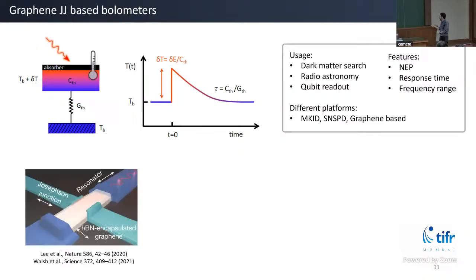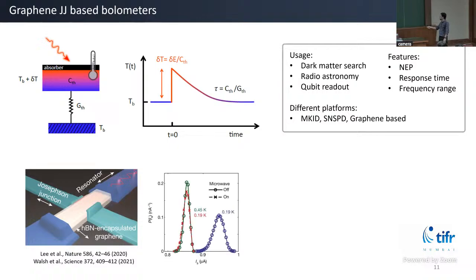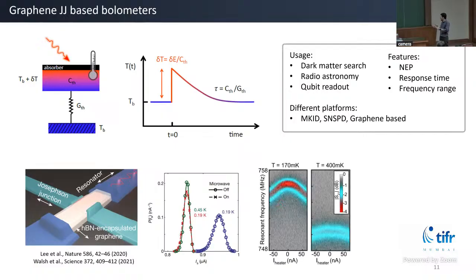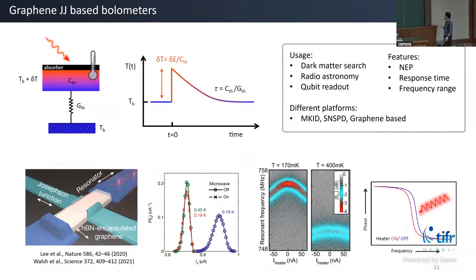Now there is a lot of interest in graphene Josephson junction devices for bolometry. These people started this work: they used a graphene JJ coupled to a superconducting resonator. Using the resonator, they send microwave photons, and the microwave photon perturbs the Josephson junction and gives a shift in the switching currents. That is your detection scheme for the bolometer. There are other variants where people incorporate the Josephson junction in a resonator and look for a change in the resonance frequency. Here I'm showing the resonance curve. Based on heating, you see a resonance frequency shift in these devices.